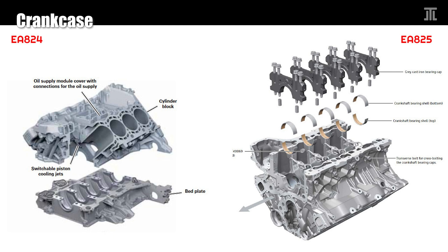The EA824 block is derived from the 4.2 FSI engine, and is an alloy block. A bed plate is bolted onto the block to hold the crankshaft, with four bolts per main bearing. In comparison, the EA825 is a eutectic block with only 9% silicon. A layer of iron is deposited onto the cylinder walls using the atmospheric plasma spraying process — the same process used by many manufacturers today under different names. The EA825 block also uses a deep skirt design, meaning the pistons do not protrude beyond the cylinder walls at bottom dead center. Rather than a bed plate, the EA825 uses individual 6-bolt cast iron bearing caps.